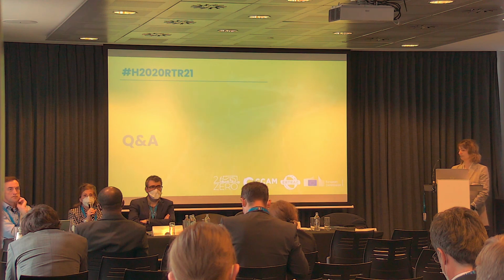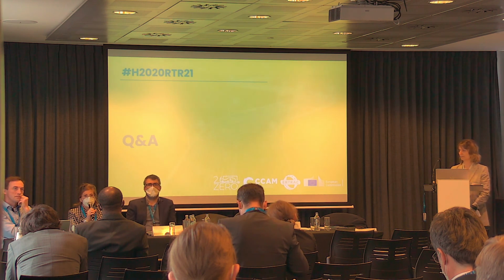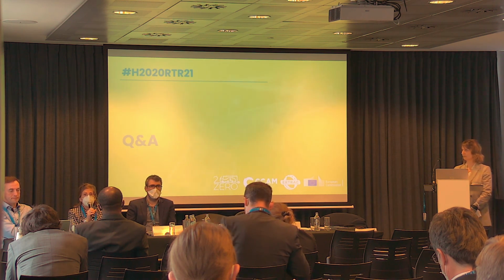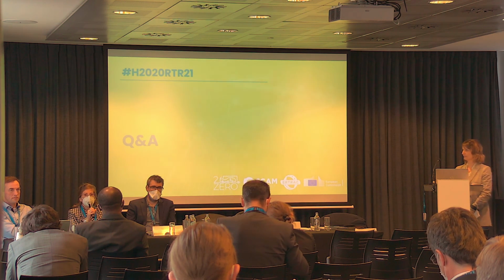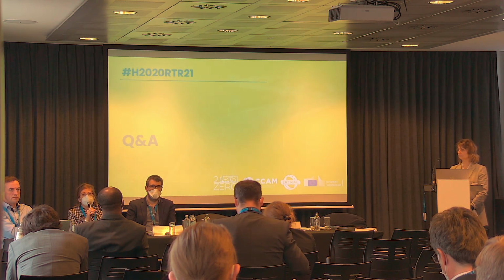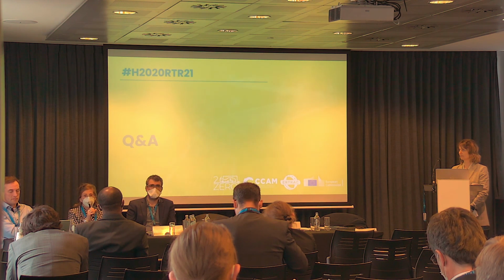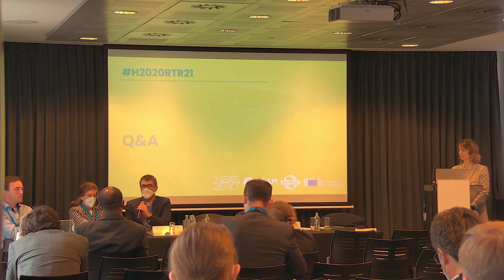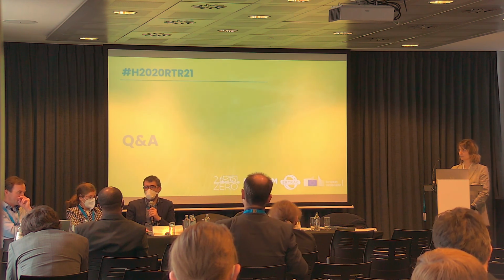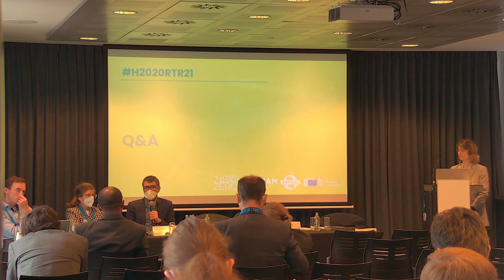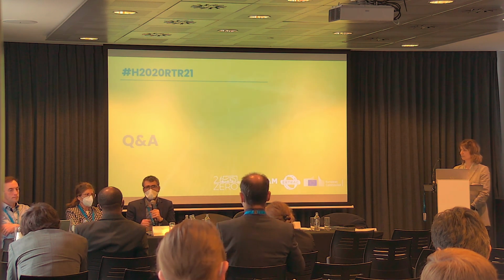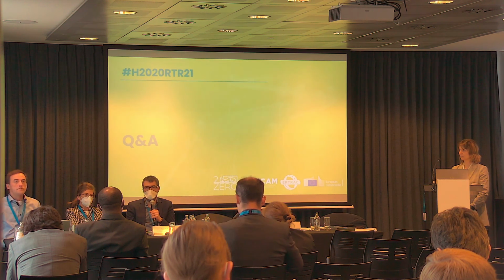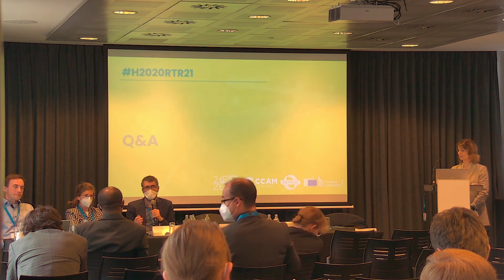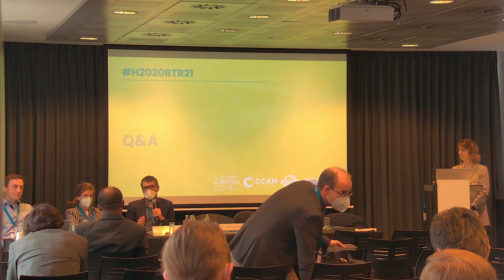But it's similar at the different scales. It's similar at the cell level scale, in which we can monitor the thickness evolution, for instance, and then we have simulations, and we compare simulation against experiment. It's the same for the materials. So we have specific techniques at all length scales, from SEM and TEM, to see the variation of material composition, especially the silicon. We know that from silicon oxide we can have some reaction path with change of the silicon oxide to silicon with lithium oxide and so on. So we are monitoring them.